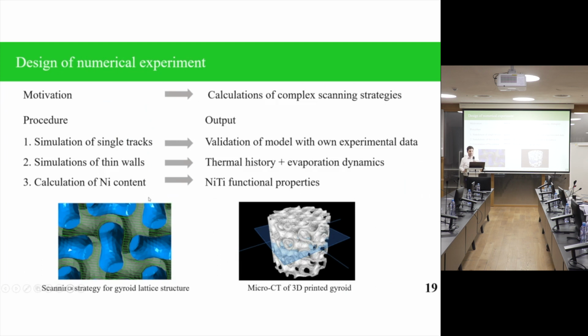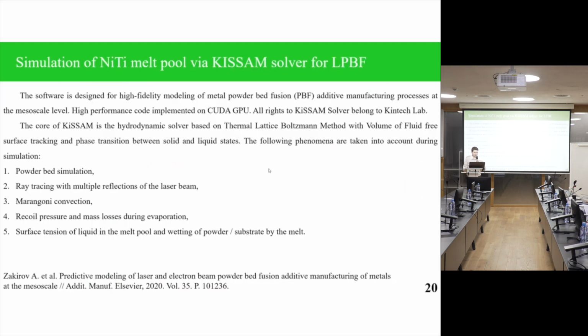In this regard, the following simulation procedures were done. First of all, the simulation of single tracks was done to validate the model. Secondly, simulation of a thin wall was performed to analyze the thermal history and evaporation dynamics. And finally, in the thin wall, we calculated nickel content, or final chemical composition, that is coupled with the resulting nitinol functional properties. All simulations in this work were performed in Kintech simulation software for additive manufacturing, or KiSSAM.